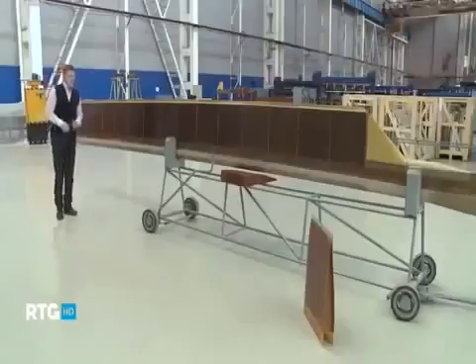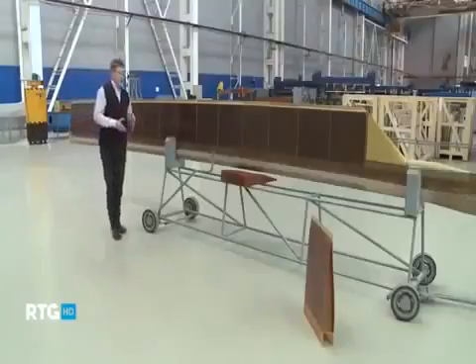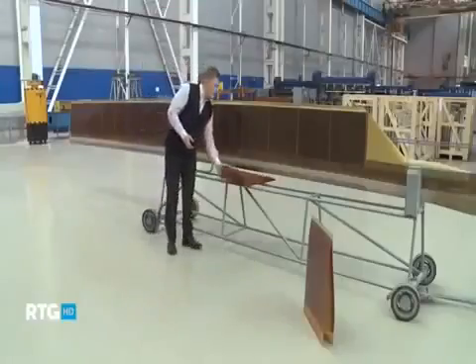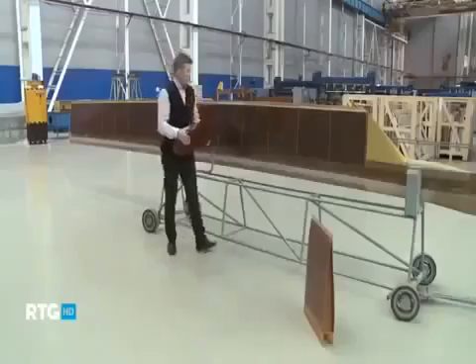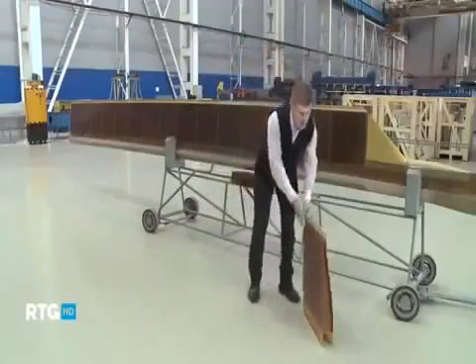First of all, reducing the weight of the main rotor makes the helicopter itself lighter, and secondly allows it to fly at higher altitudes. To reduce the weight of the helicopter, composite materials are now used in the blades, and in some cases even paper is used. It's steeped in varnish and glued together into hexagons like this. The hexagonal cells are then dried under pressure and covered with composite plates, and the result is a light and durable material.